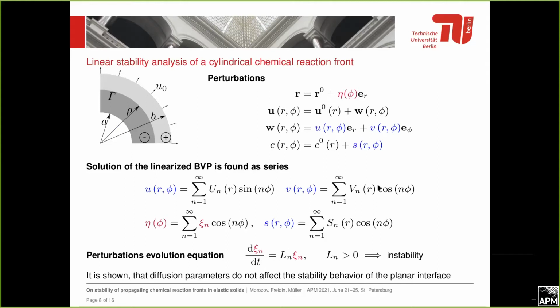So we have our solution for the unperturbed interface. Now we are going to introduce some perturbations. And as I mentioned earlier, we introduce our eta as a function of phi. Then, of course, due to that perturbation, our displacement field will be perturbed, and the diffusion field will be perturbed. And when we plug everything into our linearized boundary value problem, we can try to find the solution in series. And basically, in the end, for each wave number, we will obtain a perturbation evolution equation, which is listed at the bottom of the slide.